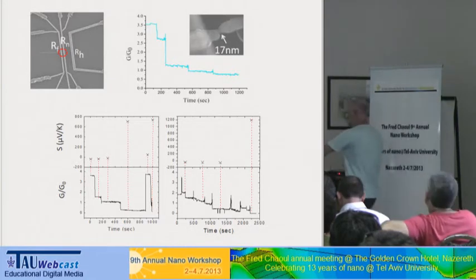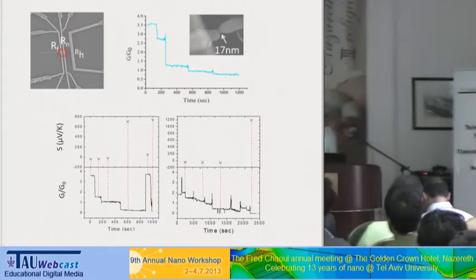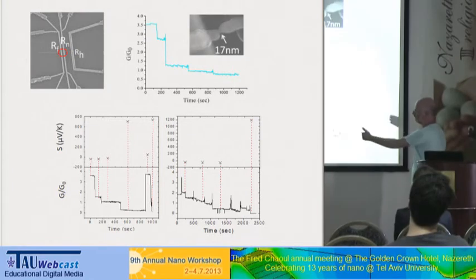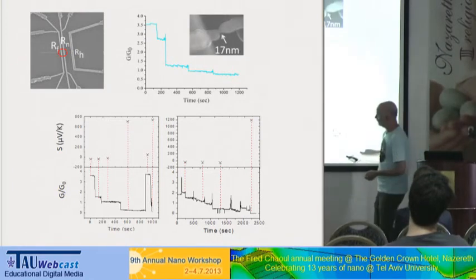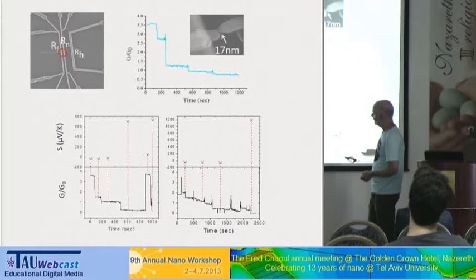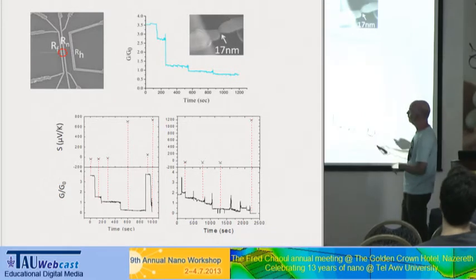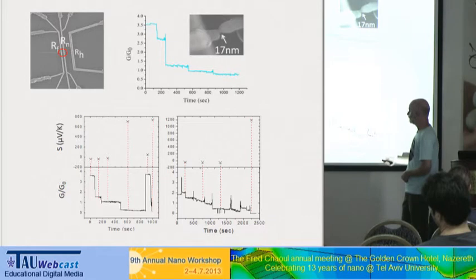Now, we can do this by changing the size of the constriction, making it smaller and larger, and we change the conductance, and at each point we stop and we measure the Seebeck. When we are above 1 G naught, the Seebeck is really low, and it's negative. But once we are below 1 G naught, the Seebeck is really large, and it's positive.